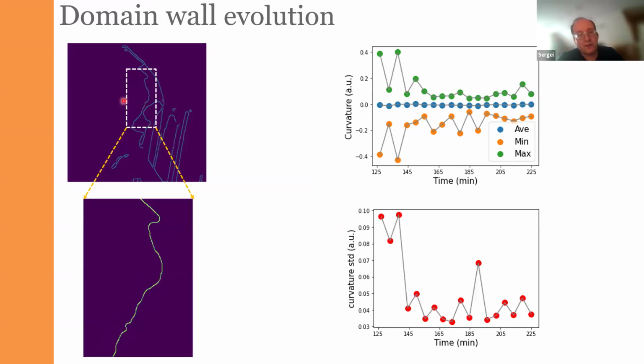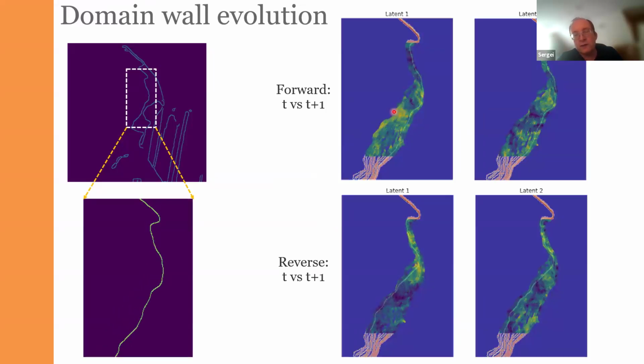And we also can enumerate how the wall parameters change during the dynamic. So if the domain wall moves, we can essentially encode the evolution of the latent variables across this domain wall. And what we see is, again, absolutely not random. You can see that there are some interesting similarities across the domain wall motion. We don't know what it means because this is the case where we looked at available data, and start to come to the conclusion that maybe we are close to overfitting, meaning that there is not enough data. But the important thing is that we see something happening, and we can even connect it to the obvious trend.